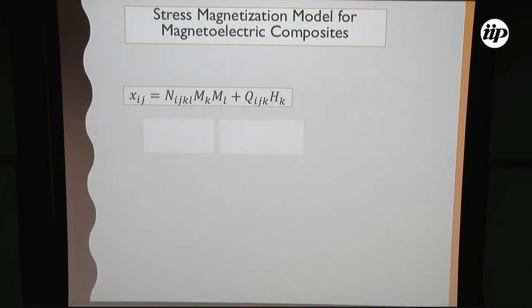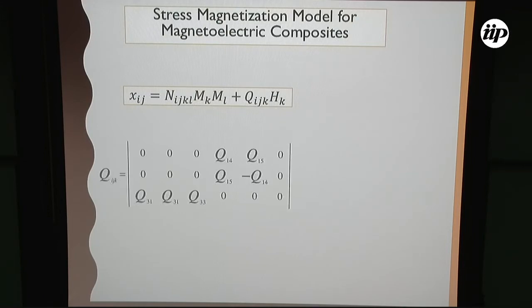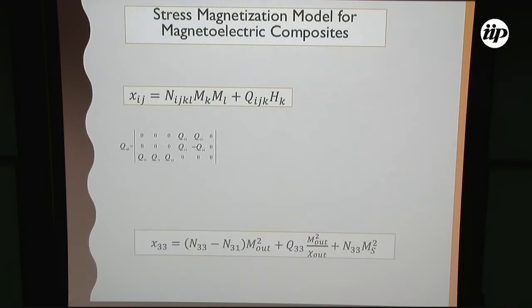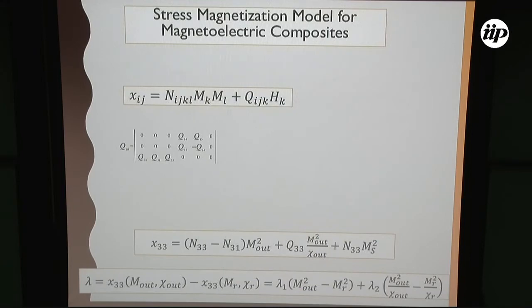However, in the case of ferromagnetic materials, it is very important to consider the associated piezomagnetic effect, associated with the spin-orbit coupling, in particular in cobalt ferrite. Using the same symmetry, this tensor is obtained and applied in this expression, and you obtain quite a different expression, depending not only on the square of the magnetization but on the magnetization and the susceptibility of the sample. So the magnetostriction coefficient is a difference of this tensor, and it's possible to describe it in this form.